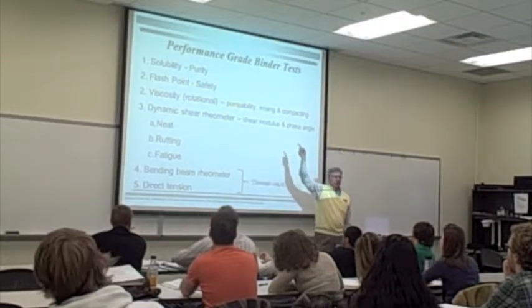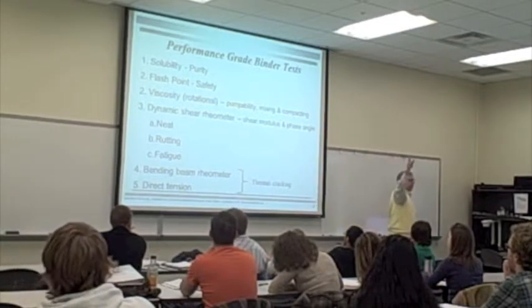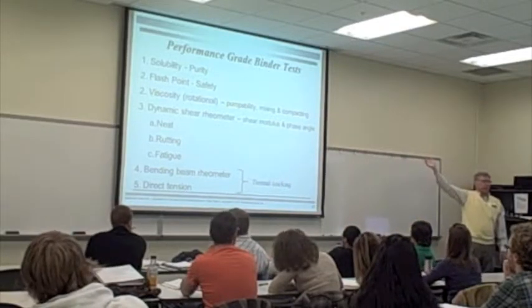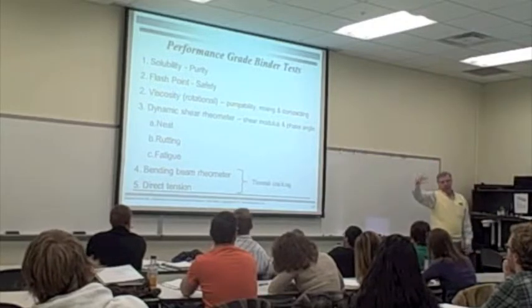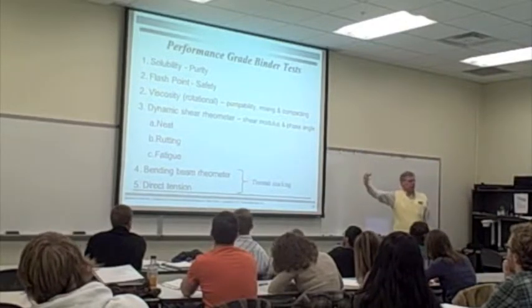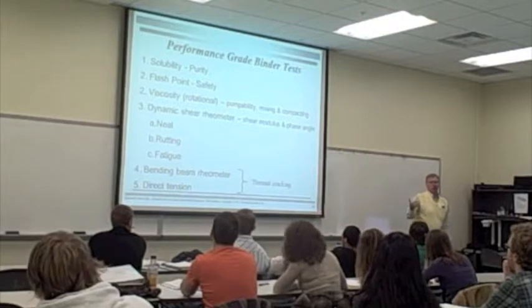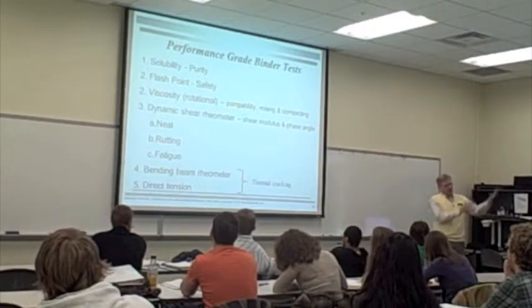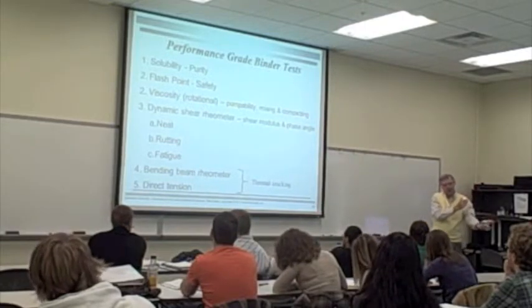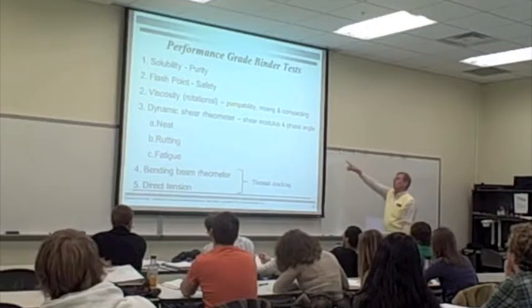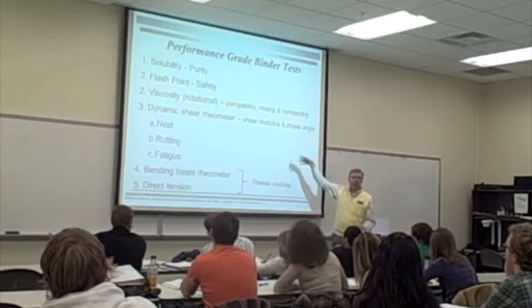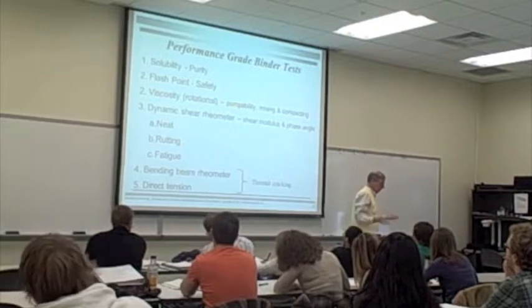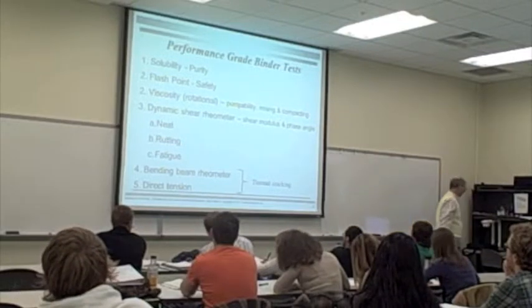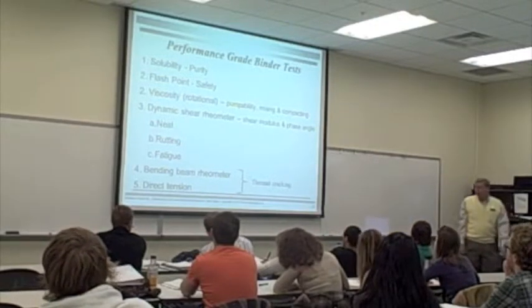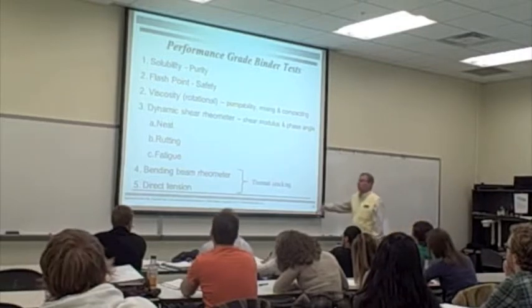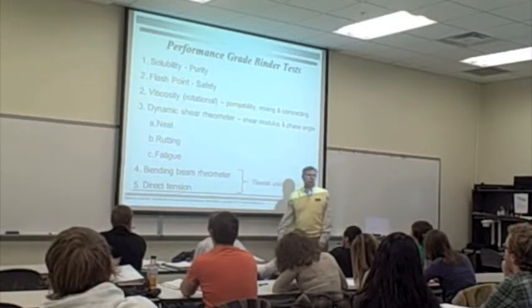But modulus is what, in the engineering world? Ratio of stress to strain, elastic modulus? Okay. In the world of viscous materials, we use shear modulus, which is shear stress over shear strain, okay? And the problem is that they don't line up at the same point, and so we've got to have this phase angle thing happening with our asphalt. And so we would go into that in more detail, but today you're not getting full coverage. This test is used to evaluate the material for the rutting and the fatigue characteristics.